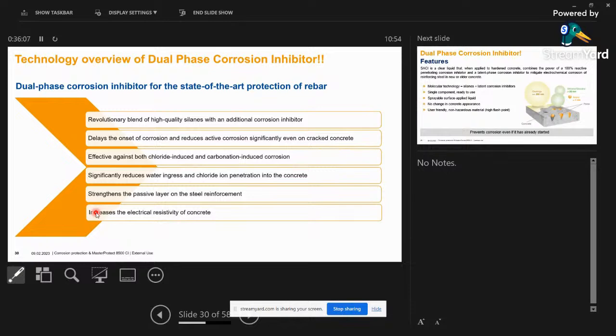So there is a mechanism by which, as per the characteristic of the silane, or depending upon what kind of inhibitor you are using, it does affect the resistivity of the concrete. If you're using silane, it greatly increases the electrical resistivity of the concrete. Why? Because silane is a hydrophobic material.